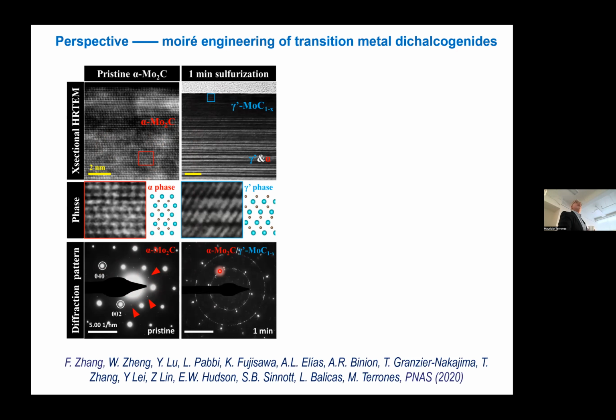we can see 2 rings here in the electron diffraction pattern, right? These 2 rings belong to 2 phases of molycarbide. One is the alpha molycarbide, that was the starting material, and the other one is the gamma prime molycarbide, which is a strained, not very common phase of molycarbide. So we can see these 2 concentric rings, and we have a combination of gamma prime and alpha molycarbide.